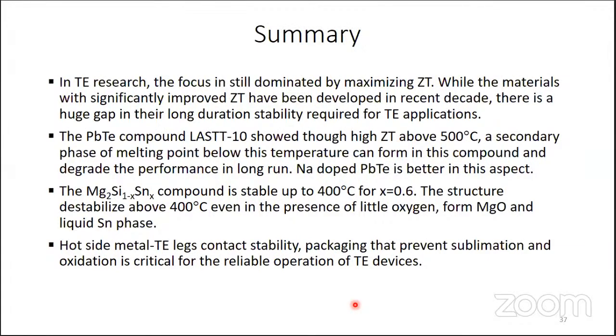So here we took two materials, lead telluride and Mg2SiSn, and we found sodium-doped lead telluride is better than the latter, even though the ZT is very good. And by combining it successfully with packaging techniques, bonding techniques and a diffusion barrier, we were able to make a module, and now this module can operate for a very long duration without any degradation up to 400 degrees Celsius reliably.